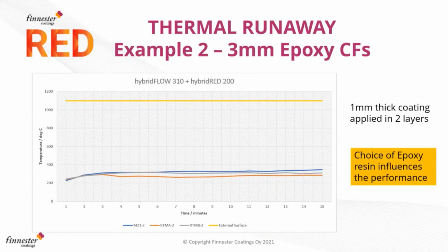Second example, here we've been looking at different epoxy carbon fibers and showing that the choice of the epoxy resin has quite an influence, as you'd perhaps expect, over the performance. But the same characteristics, a very flat curve, a very uniform amount of temperature being blocked out, no dramatic changes, no sudden breakdowns of that ceramic shield and thermal barrier. Surviving, in this case, 15 minutes at over 1000, this is 1100 centigrade with our two-coat system. Again, just 1 millimeter thick, giving a very significant reduction in the thermal properties on the inside surface compared to the outside surface.